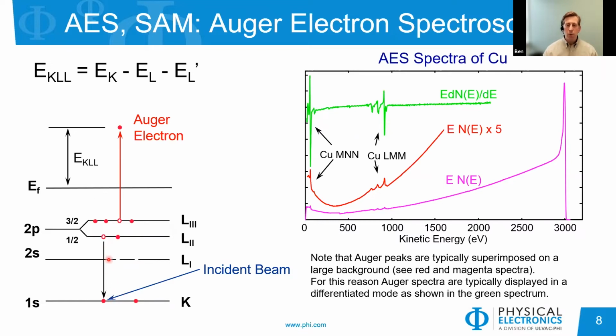And in doing so, it will release a given amount of energy related to the difference between these two energy levels, which could be transferred to a third electron. And if that is sufficient to overcome the binding energy of that orbital, then this could be ejected. And so this is the Auger electron. So it is a 3-electron process for Auger spectroscopy.